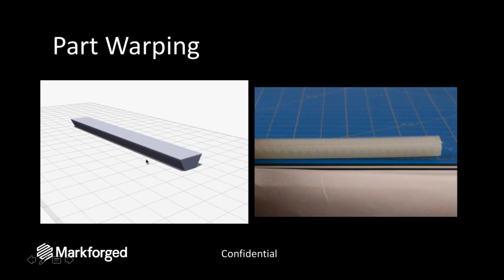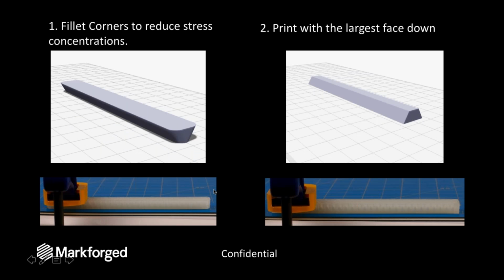So this test part that I used to test warping, just by rounding off those edges, it ends up warping much, much less than it originally did, as you can see over here. The second is sort of intuitive for a part like this, but for larger, more complex parts, may not always be the first thing you think of, which is just to print with the largest face down. This means that there's not as much of a buildup around the corners, just because the layers that are being stacked are smaller than the ones they're being stacked upon. So printing the part upside down also significantly decreased the warping.